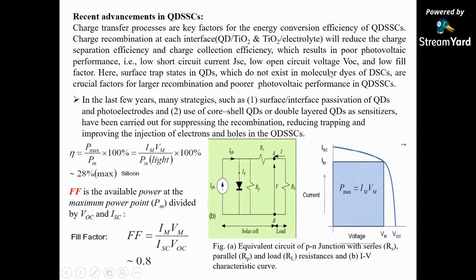And there are recent advancements in surface and interface passivation of quantum dots, and core shell QDs are being used, because of which recombination at each interface will be very less, and the charge separation will be maintained. You see, charge separation is very much needed, so this is happening by the interfaces at the quantum dot to the semiconductor nano layer, and nano layer to the electrolyte. And the efficiency can be calculated by this P maximum. This is the I versus the voltage curve, and there is a point here where you can get the IM and VM maximum.